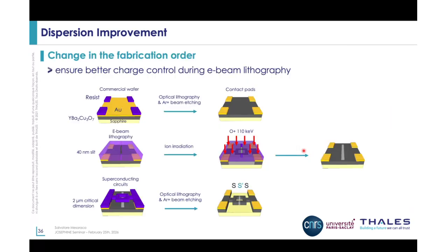So, for example, in the same line of thought, we are applying a change in the fabrication process, where instead of making the Josephson junctions on an etched YBCO, where there is a very tiny amount of YBCO with just the superconducting circuits, we make the junctions on a plain YBCO, so we invert the optical lithography steps in order to have the YBCO, which is still a bad conductor at room temperature, but still a conductor, that can help the evacuation of the charges during the e-beam lithography and the irradiation. And this is proving to be a good choice because we're observing very good results that hopefully will be shown in the future. I think that was the end of it.